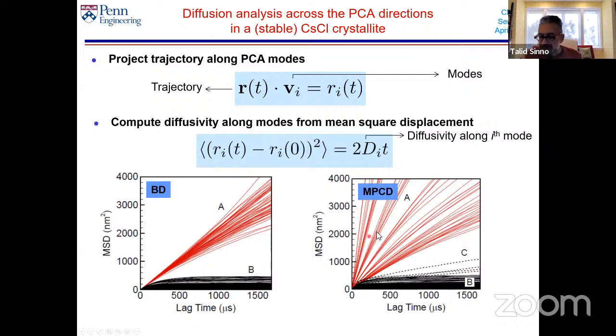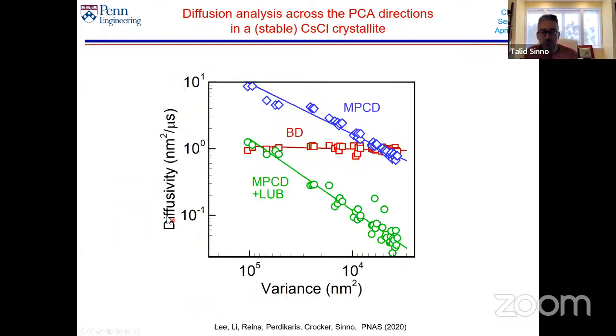When you do this with fluid mechanics included, you get a much broader dispersion of diffusivities. You get high diffusivities, medium diffusivities, low diffusivities. It's a lot more dispersed. If you look at what is a high diffusivity versus a low diffusivity pathway, you can plot all the diffusivities along the different variances, along the different eigenvectors. So in BD, all the different modes, the x-axis is just modes, I'm just using variance as an axis, all the diffusivities are the same. When you have fluid mechanics, the diffusivities now vary.